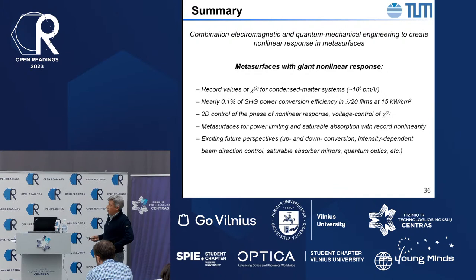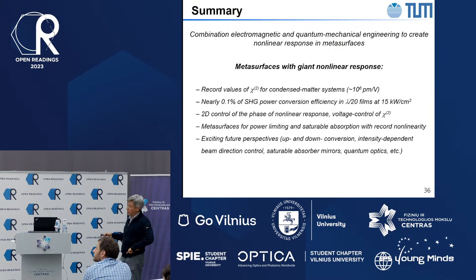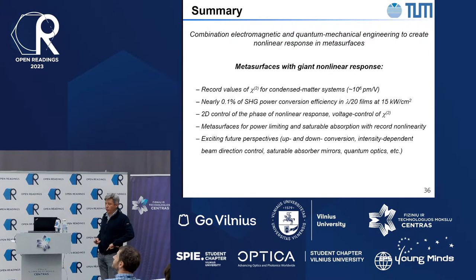So what I have shown you is that by combining the concepts of metasurfaces to the fullest, where we use both electromagnetic design of the local nanoresonators and the quantum mechanical engineering of the material itself, you can produce metasurfaces that show giant nonlinear optical response, which now represents, to the best of our knowledge, the highest nonlinearity in the middle infrared spectral range out of everything available. The measured values of nonlinear response are 1 million picometers per volt. This is to be compared, for example, with typical values of nonlinear crystals of only 10 picometers per volt. So we are 100,000 times higher than that.